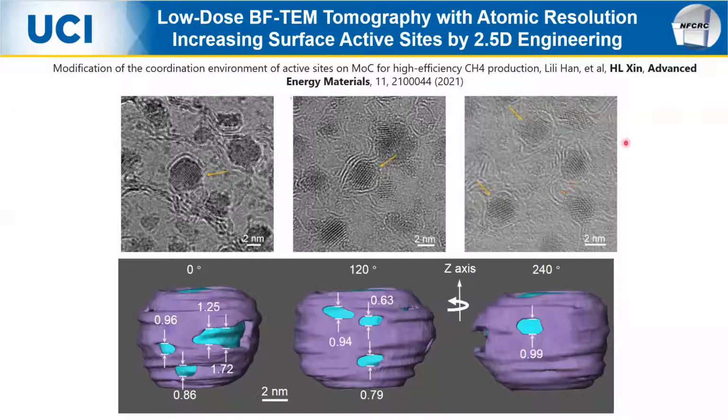And even more interesting, the development of a low-dose bright field TEM. HAADF STEM is really good for quantitative imaging of thick and heavy materials. However, for light elements such as carbon, graphene here, bright field TEM has its own merit. Due to the phase contrast here, we're able to reconstruct the whole graphene structure that wraps around a very small nanocluster that shows all these holes that are active sites for this catalyst.